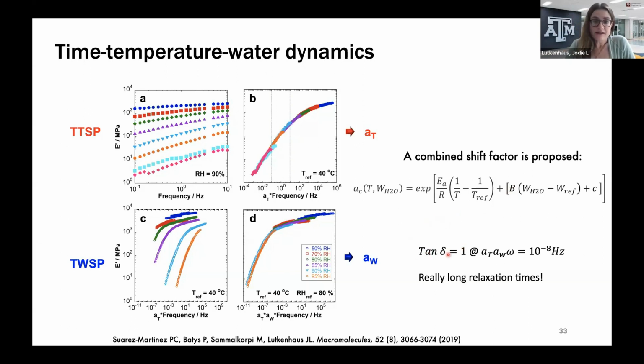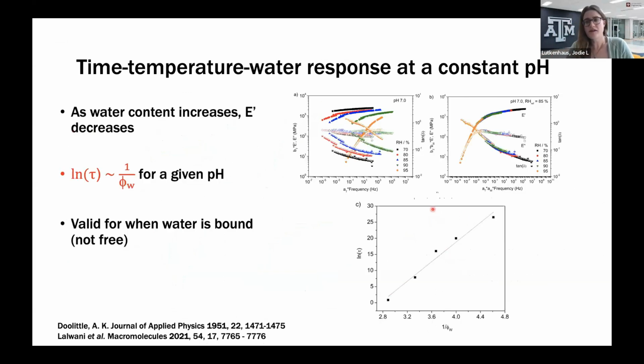Now, the relaxation time can be taken as where the tan delta, which I'm not showing here, is 1. And we're getting really long relaxation times. These complexes are very brittle and very tightly bonded. So they need long times to see any relaxation. Now, what we were able to do was also take a relaxation time as the crossover of the E prime and E double prime data. And that gives, from that frequency, we can get a relaxation time.